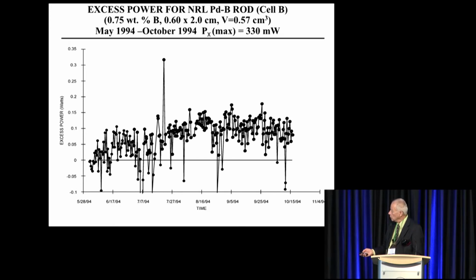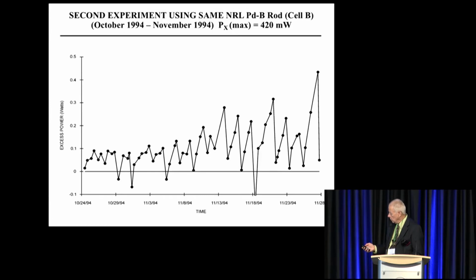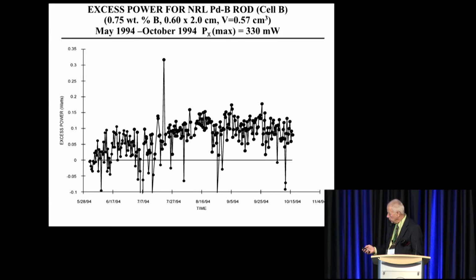Some of the points look like they're off. I went back and looked at this point. Well, I changed things around a lot, and on that day, I raised the bath temperature to 50 degrees, so the cell was well over 60, and so I think that's the true effect. I didn't know it at the time, but Fleischmann later told me all their large effects came at cell temperatures above 60 degrees Celsius. He thought that was sort of a threshold to get the larger effects. Should explain some of the low effects too.